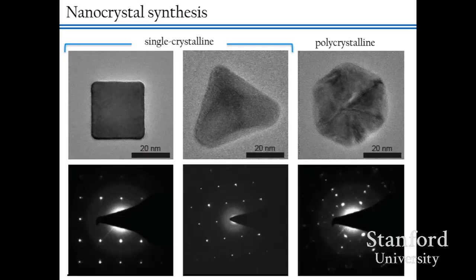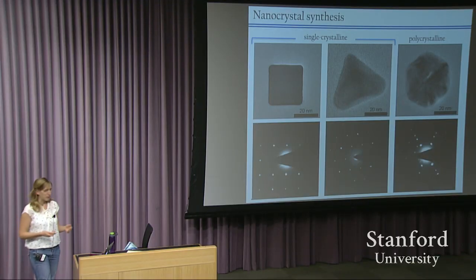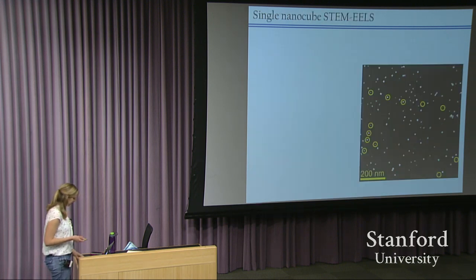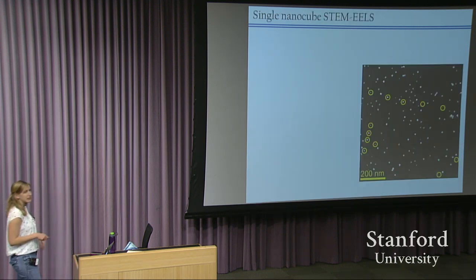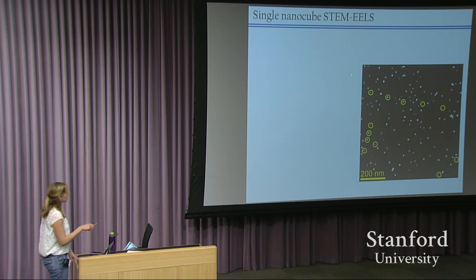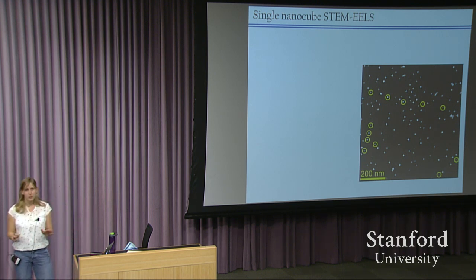I want to show you just three different classes of nanoparticles, basically a square, a prism, and an icosahedron. The square and the prism are single crystalline nanoparticles, so by looking at these two, we can deconvolve the effects of shape. And then this icosahedron is polycrystalline, so we can look at how different crystallinities might impact the storage capabilities. So we disperse our nanoparticles on an electron transparent grid, and then we identify individual nanoparticles that we want to look at more closely. And like I said, we can image each of these nanoparticles with very high spatial resolution.